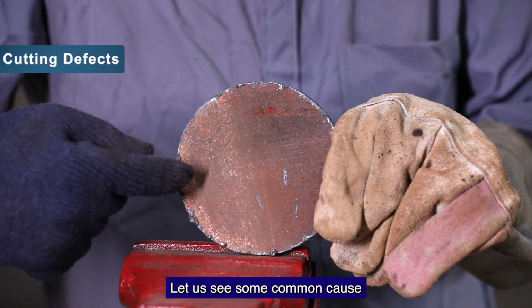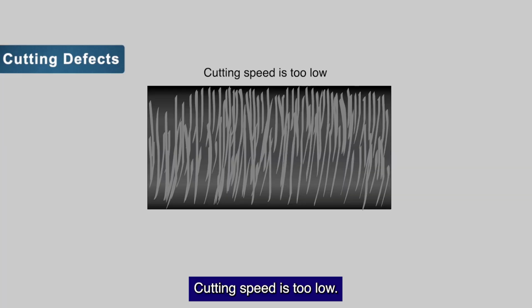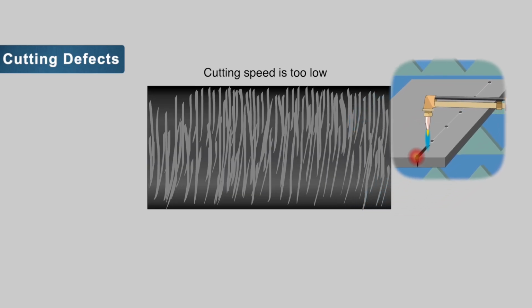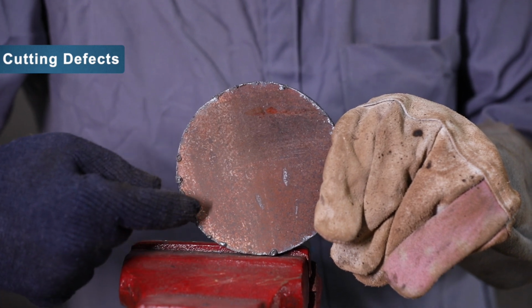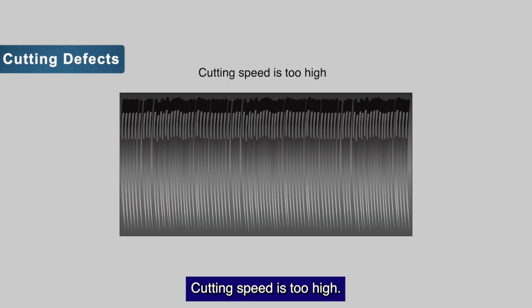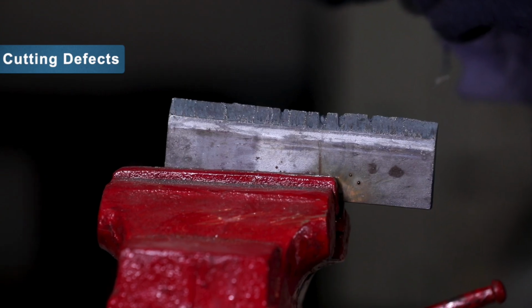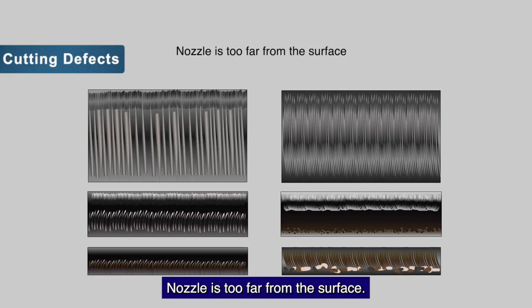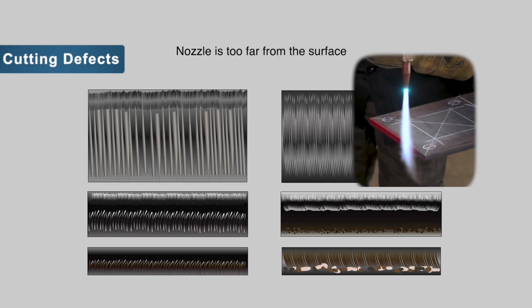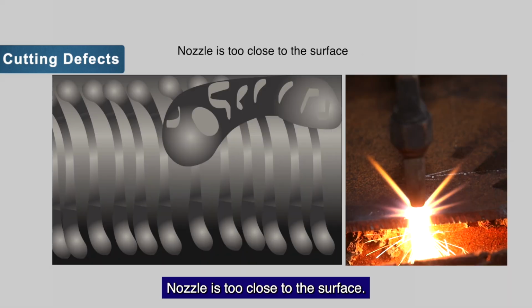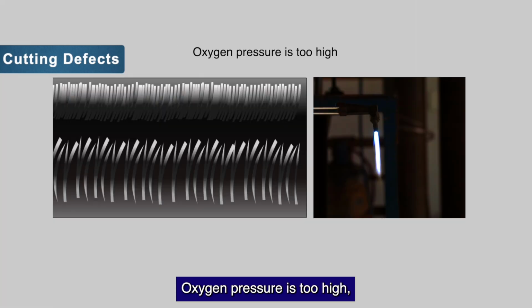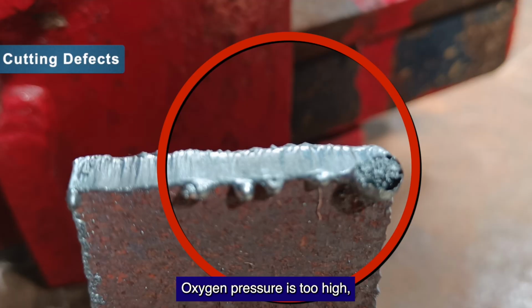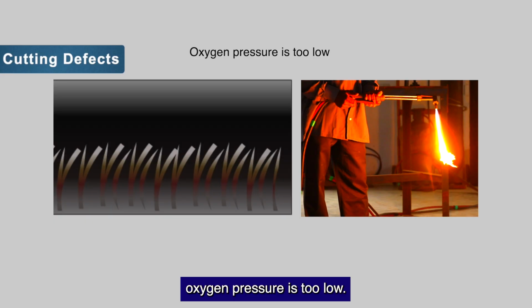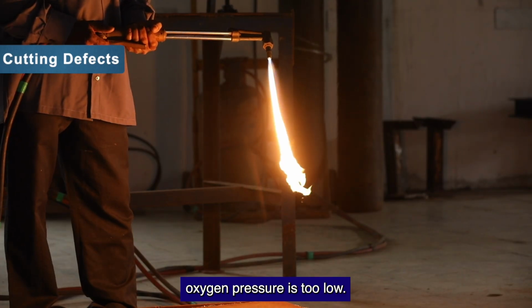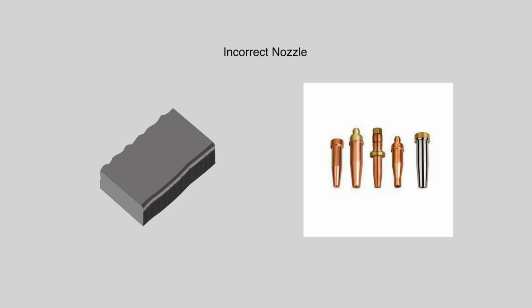Let us see some common causes of oxy-acetylene cutting deficiencies. Cutting speed is too low. Cutting speed is too high. Nozzle is too far from the surface. Nozzle is too close to the surface. Oxygen pressure is too high. Oxygen pressure is too low. Excessive preheat flame. Incorrect nozzle.